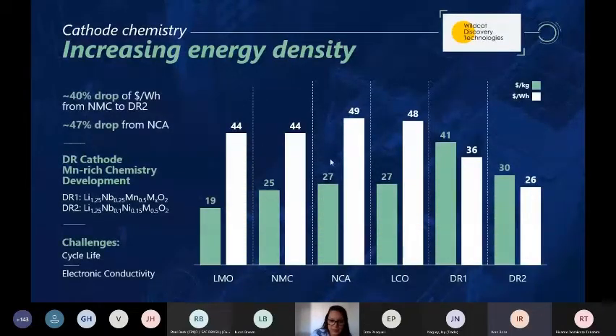When you compare the price per energy of the second material, with low content of lithium, with other commercial ones, the disordered material number 2 here is 40% and 47% cheaper than the NMC and the NCA materials. We can consider these disordered rock salt structures promising candidates for lithium-ion battery cathodes, but we still have challenges related to the cycle life and the electronic conductivity.